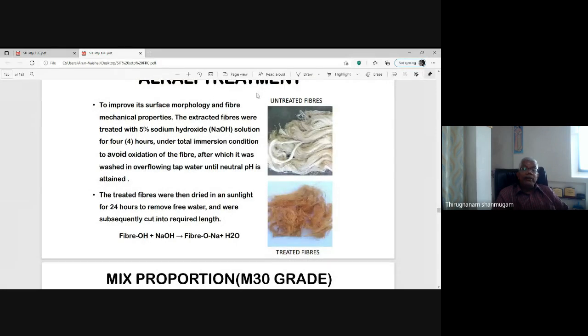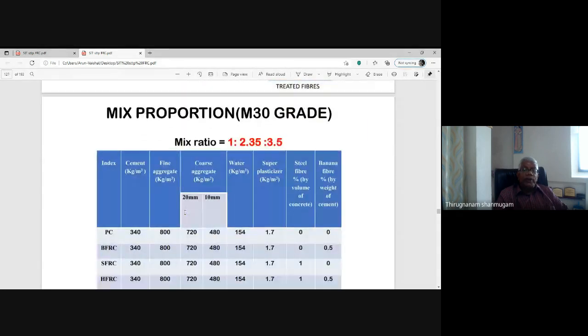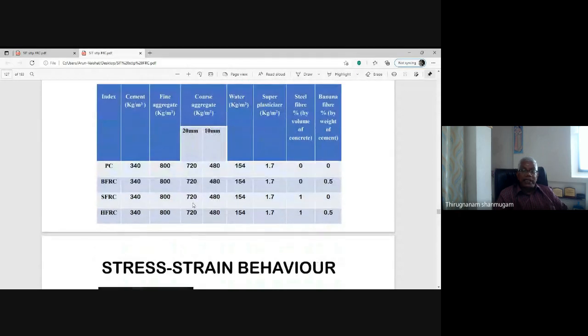But these fibers will not be used as they are. They have to be treated to improve their surface morphology and fiber mechanical properties. The fibers were treated with 5% sodium hydroxide solution for 4 hours under total immersion condition, after which they were washed in overflowing tap water until neutral pH is obtained. The treated fibers were then dried in sunlight for 24 hours to remove the free water and were subsequently cut into the required lengths. So this is the view of the banana fibers. Mix proportion is adopted for M30 grade concrete.